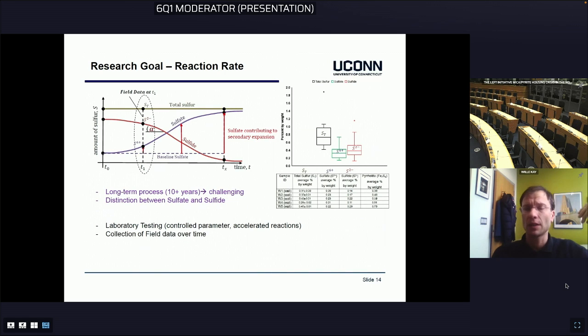And so the concept behind this is that we know there's a certain total sulfur. We can measure this in the concrete, and this total sulfur comes from the sum of the sulfate, the purple line, and the sulfide, the reddish line there. If the sulfide, for example from the pyrrhotite, oxidizes, then the sulfides transfer into sulfates. The dashed line is the baseline sulfate coming from the cement, which is not of our concern, but the added sulfate, which comes from the sulfide transformation through the oxidation, could lead to a secondary expansion and then to further cracking and deterioration.